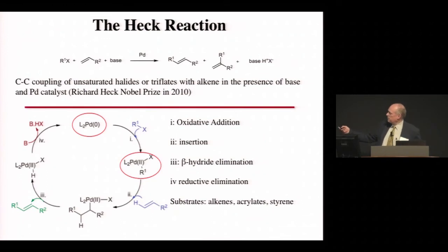And in this case, we have a catalytic cycle that goes through here. And the ones I have circled in red are the two resting states of the catalyst. That is the states where the catalyst kind of resides. And so if we don't have any of this RX group, the thing that does this oxidative addition, we have the palladium in the zero valent state. That is, it can be kind of reducing. But if this is around, it will oxidize it to the palladium-2. So let's say if we have some of this halide around, we'll basically have this be the resting state. And now if we feed it some of this alkene, it'll quickly zip through these species. It does an insertion, beta hydride elimination, and then deprotonation. It'll quickly generate over here and then slowly bleed back to this state if we have an excess of this around.